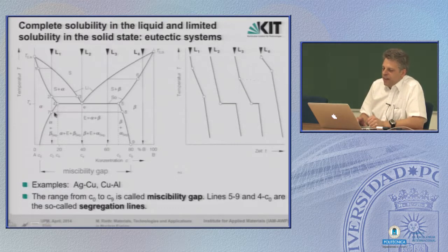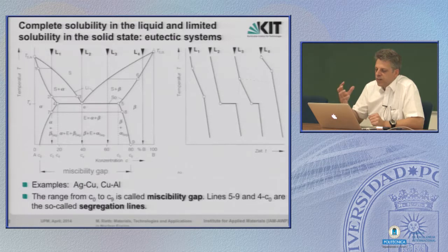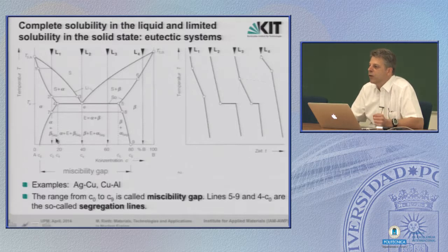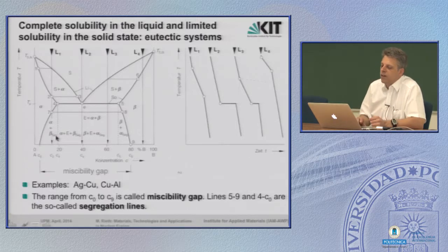And if we again transit over this line here, then this alpha solid crystal decomposes because both components are not soluble anymore. So in that case, a second phase precipitates inside the crystal. That's the beta phase. And since it's a segregation, it's indexed with this name.